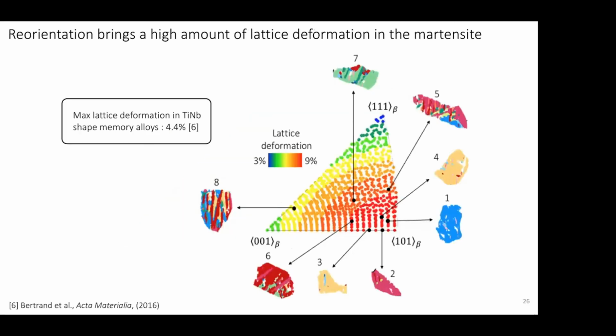As I said, you can express this interaction energy as an energy, but also as a deformation. That's what we did on this IPF. You can see that at the maximum, we can reach 9% of deformation. If we compare that with the value given in the literature for a classical shape memory alloy, titanium niobium, at the maximum we can find 4.4% of deformation. So in fact, in our martensite, the deformation that can be reached thanks to reorientation is quite high.